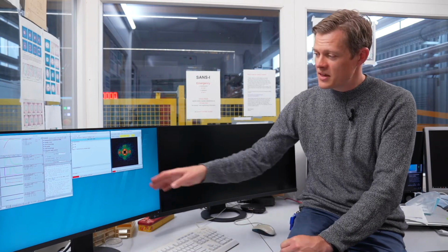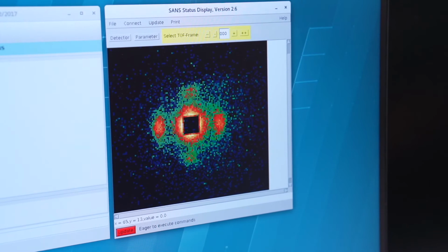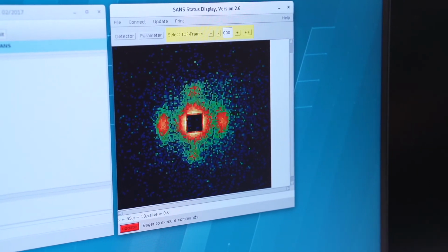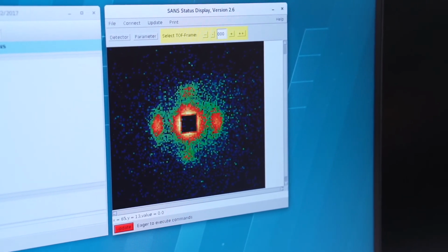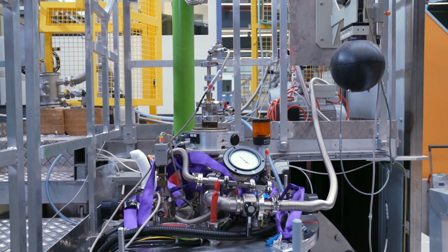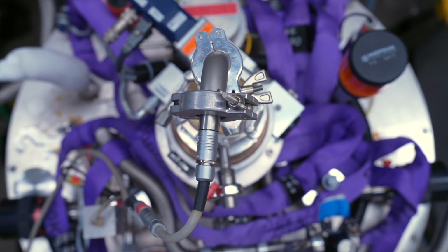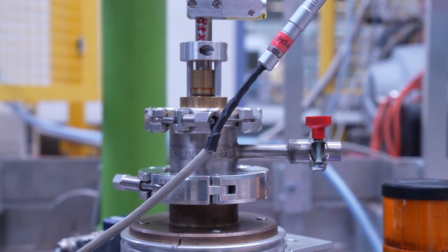When we perform the diffraction measurement in this geometry, we see that the SANS diffraction pattern is dominated by two diffraction peaks. This is due to a spiral type of magnetic order that propagates along the field direction and which could not be observed in the first geometry. This ability to rotate the magnet between geometries provides the opportunity to study multiple modulating structures inside a single sample in a single experiment. For further flexibility, a motorized stage on top of the cryomagnet provides in-situ rotation of the sample inside the magnet, and thus independent from the direction of the magnetic field.